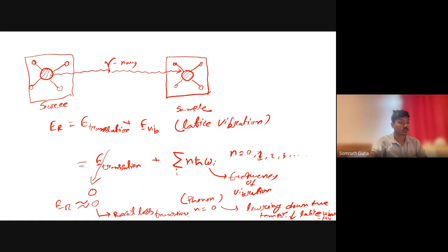Okay, recoilless transition. Now we can say that recoilless transition is required for Mossbauer spectroscopy. But we will not get a perfect recoilless transition because we are not going to absolute zero. Until and unless absolute zero, there will be a lattice vibration, and that lattice vibration is actually responsible for some recoil energy, and we lose some recoil energy. But by using low temperature and the solid matrix,